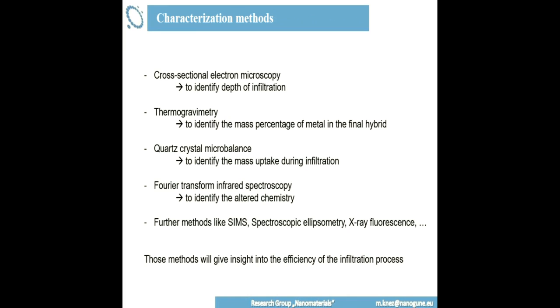You can do thermogravimetry to identify how much of your metal is inside of your final hybrid. It's actually a hybrid material. That's what I didn't mention here. Your polymer, which you infiltrate with inorganic material, if it binds, is going to be a hybrid material. So if you then have your hybrid material, you do TG, and with TG you can have the mass percentage. You can use in situ quartz crystal microbalance to observe the mass uptake during the process. It's a possibility. Of course, you can look into FTIR for the altered chemistry. You can see chemical groups of your polymer backbone being consumed or altered with your inorganics.